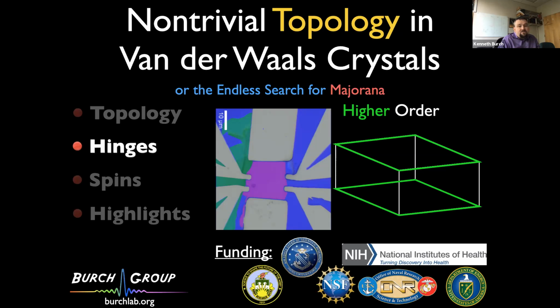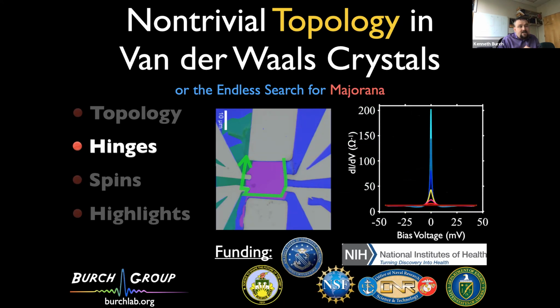And what I'm going to show you is that with the idea that the contacts that touch the hinge should therefore see enhanced conductance due to this additional mode that's sitting there on the hinge, whereas the ones that touch the bulk would just look like normal Andreev reflection. And indeed, what we saw is from the contacts that touch the hinge, when we measure the differential conductance versus voltage, we see an enormous zero bias peak that shows up in the superconducting state. And we take as evidence of the fact that there is indeed this hinge mode there in this system.